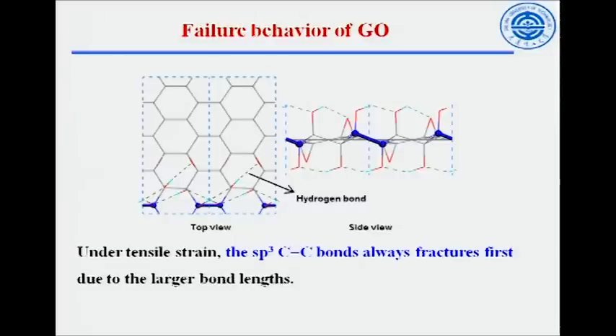We further look at the failure behavior. Where did the first bond break? And we find that in tensile strain, the sp3 carbon-carbon bonds fracture first, because this bond is longer than the other bonds.